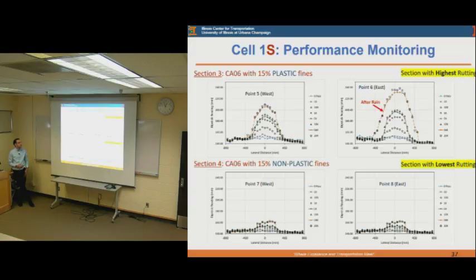But overall, the section with the highest rutting was the section that had the 15% plastic fines, and especially the rutting was high after the incident of rain at some of the points where the rutting was significantly increased after the layers got wet. While the section that performed the best out of all these sections was the section with the 15% non-plastic fines, and it had the lowest rutting. And this also conforms very well with the LWD deflections, and FWD deflections, sorry, where the sections that had the highest rutting also had the highest FWD deflections, and vice versa.